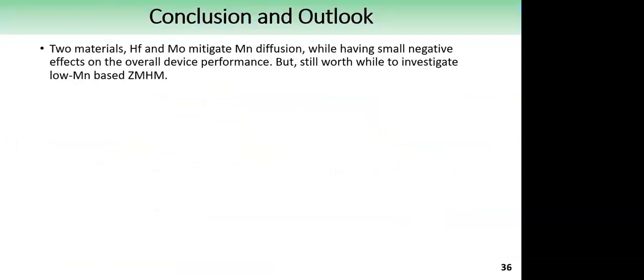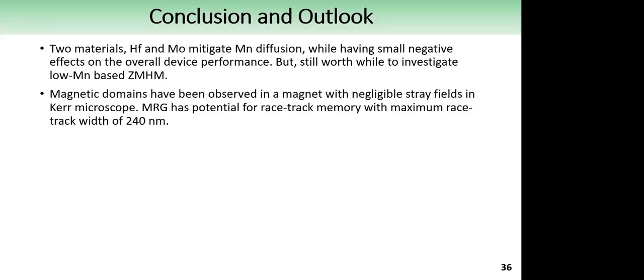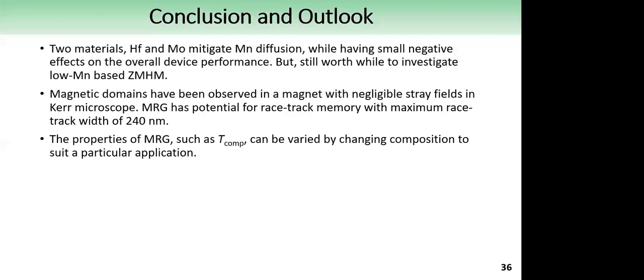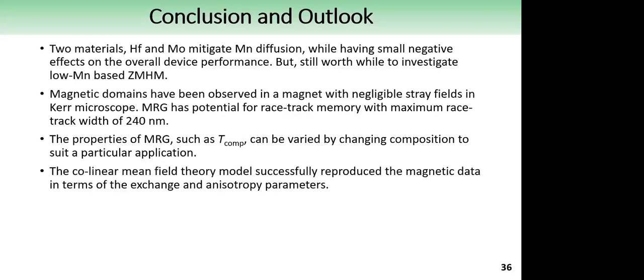First, 2 materials, hafnium and molybdenum, were found to be effective in mitigating manganese diffusion while having small negative effects on the overall device. But it is still probably worthwhile to investigate low manganese-based zero-moment half metals to minimize this issue in the first place. Magnetic domains have been observed in a magnet with negligible stray fields in the Kerr microscope. And MRG has a potential for racetrack memory with maximum racetrack width of about 240 nanometers, according to our results. The properties of MRG, such as compensation temperature, can be varied by changing the composition, and we can therefore suit it for a particular application.